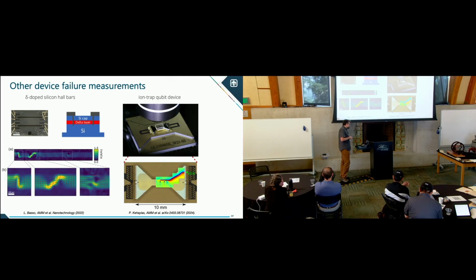And I think more interesting, most recently, is the ion trap qubit devices that Sandia fabricates, which is this bow tie. Now, these are supposed to have a lot of electrostatic gates on them, so they're not supposed to have any current. But they were finding failures in their devices where they were drawing current through these electrostatic gates, from a bulk probe test, like a multimeter. So they asked us, can we find where this actually happened?